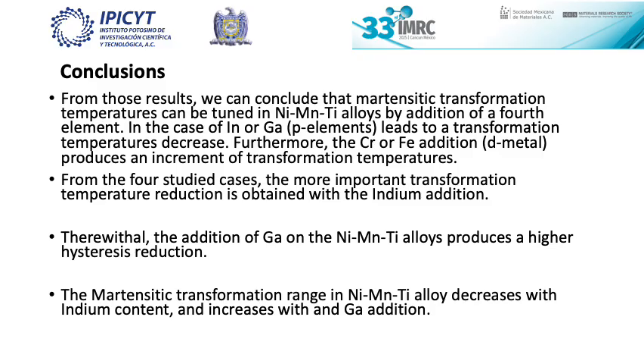Furthermore, the addition of gallium on the nickel manganese titanium alloys produces a higher hysteresis reduction. The martensitic transformation range in nickel manganese titanium alloy decreases with the indium content and increases with the gallium addition.